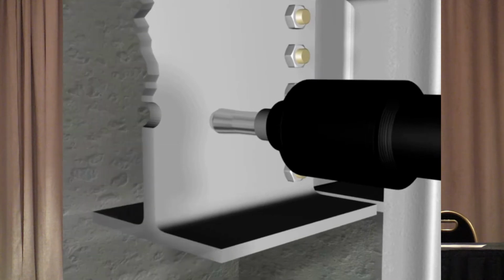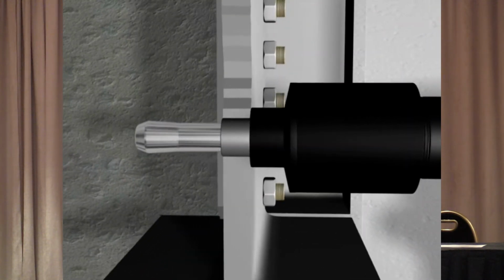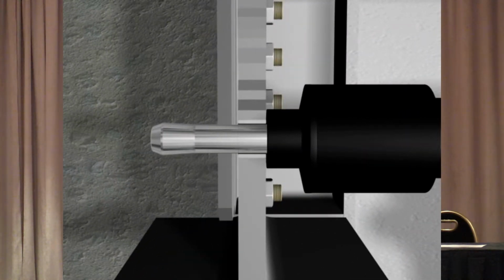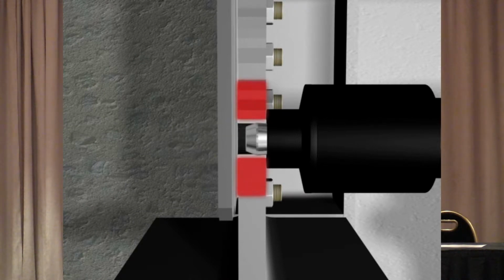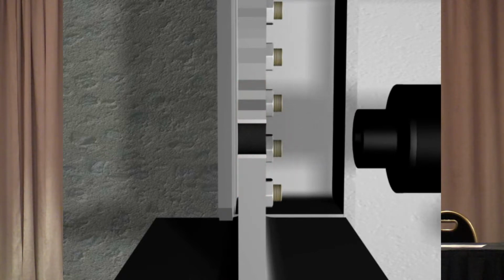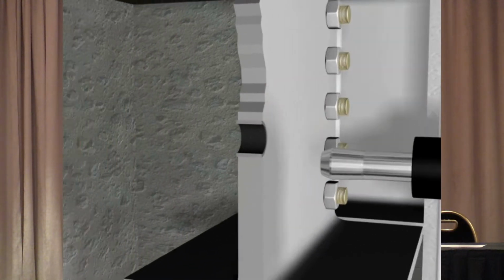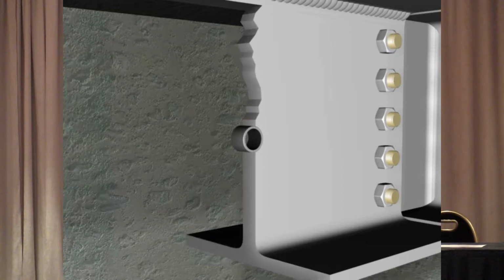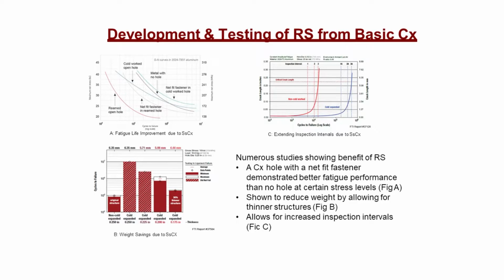And again, we are going to install this both plastically deforming the bushing and the parent structure and getting that zone of residual compressive stress. So that crack tip is actually caught in that zone of compressive stress, seriously reducing the stress intensity factor and retarding further growth. From CX to protect fastener holes all the way to what we're doing now is through a series of developmental testings. I don't want to spend a lot of time on these tests because they're for the basic CX. But we looked at the fatigue life improvement due to cold expansion.